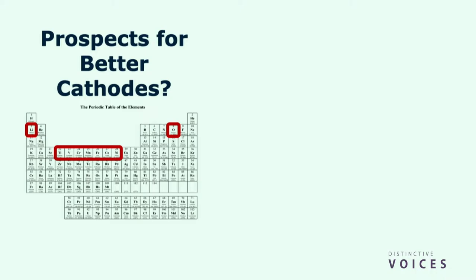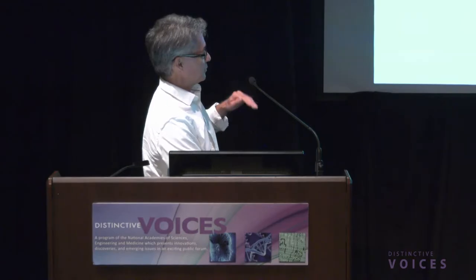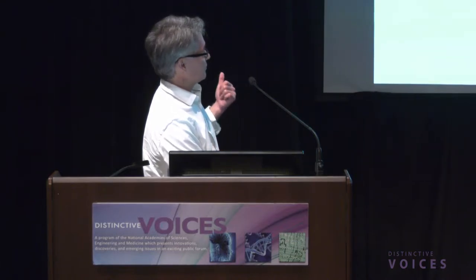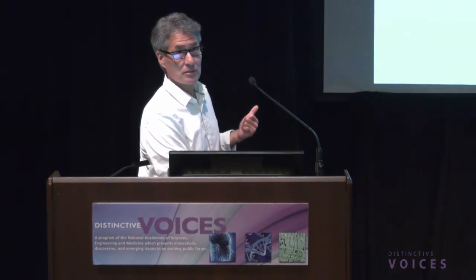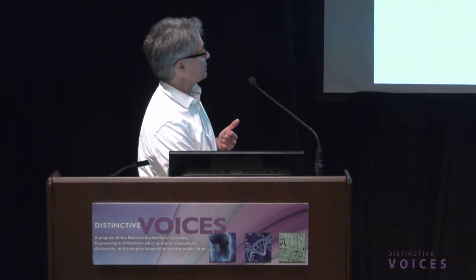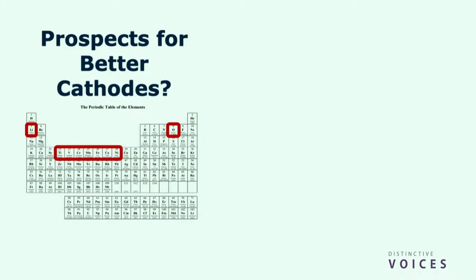It has to contain lithium. When lithium-ion batteries are made, the lithium is actually in the cathode. Probably should have oxygen. And then it has to consist of a transition metal, meaning it can go through multiple valence changes. And it has to be reasonably light and abundant. So that really means that we have to be in this region in the periodic table. Titanium doesn't have the right quantum mechanical properties. The voltage is too low. Vanadium is problematic for the reasons I just said. Chrome has toxicity issues, so it's really down to manganese, iron, cobalt, and nickel.